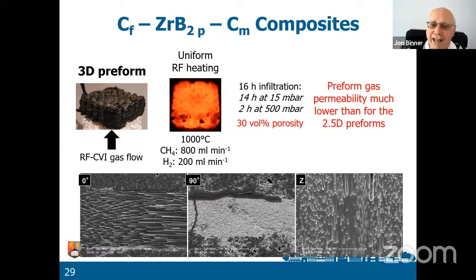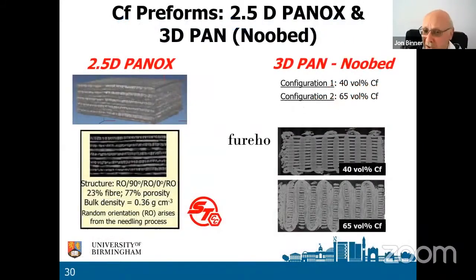And if we can't get the gas to flow through the sample, then we're not going to be able to deposit the matrix. So it's much, much slower because the preforms have much less gas permeability. The advantage they potentially offer is improved mechanical performance.